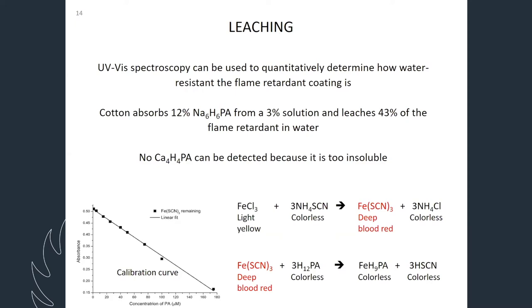And that we have as a standard solution. We know the concentration of the material there. Then if we add phytic acid, which is known to bind very strongly with iron, phytic acid forms a stronger complex with iron in a quantitative way. So the red color will start disappearing. As you see on the left, we have higher absorbance when there is no phytic acid added, and I am adding more and more phytic acid. So the absorbance is decreasing with increasing amount of phytic acid.